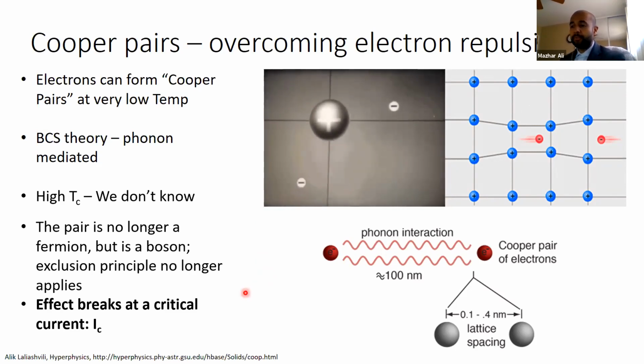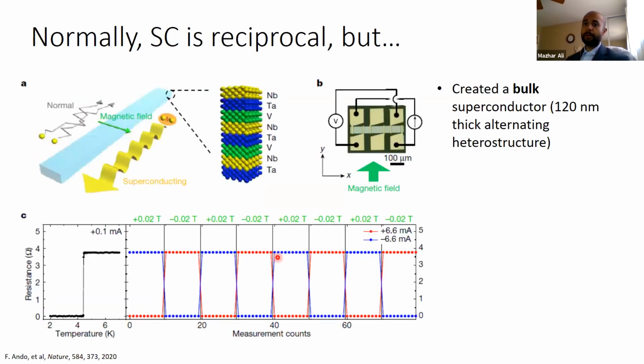But also, you can break the superconductivity by putting too much current. That's known as the critical current through your superconductor. So the critical current is important. Now, normally, superconductivity is reciprocal, as in, if it superconducts to the left, it'll superconduct to the right. That's what you'd expect for basically any material.